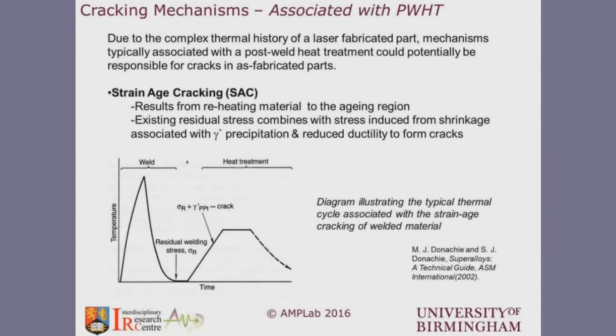Then the fourth mechanism that we're aware of in nickel superalloys is known as strain age cracking, where typically if you weld the component, that welding process with its rapid heating and cooling phases will result in the formation of residual stresses.